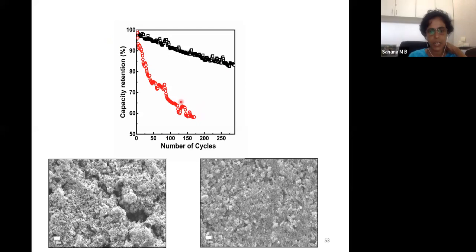The reason is, if you open up the cell after 100 cycles and see what happens, in one of the cells there is no connection between particle to particle. You can see big cracks, since these materials are soaked in the electrolyte. Because of the liquid, it can move, it can segregate separately. So you can see that there are large cracks over here, which is minimum in this case. These are the ones which determine the cyclic stability.